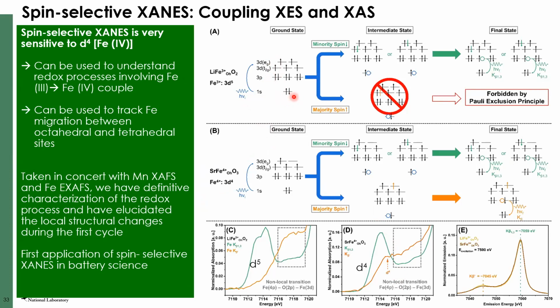There are one of two things you can do. Typically, Hund's rule and Pauli's exclusion principle would say that you can have only 2 electrons in the same orbital, and their spins must be opposite. It is often represented by the up spin or the down spin. So if the X-ray is able to populate a down spin, that is, you take this down spin from here and put it into this d orbital, you reach an intermediate state which would be allowed because the 2 electrons would have opposite spins. And then, because you have pumped an electron out of the K shell to a higher shell, the system relaxes.